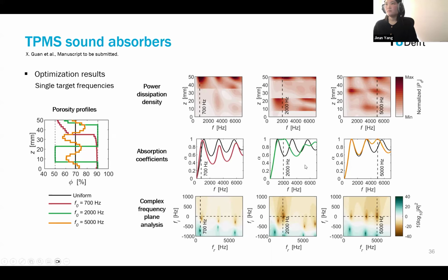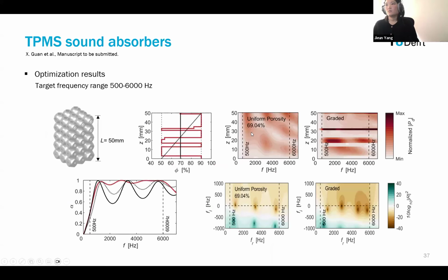And also this one in the middle was a little bit of an extreme case, because we were trying to improve the sound absorption coefficient, which was at quite a low value, to a higher one. So the optimization produced this very jumping profile to move this peak frequency and also increase the dissipation. Yeah, so we thought it helped a little bit in understanding how we obtained this very jumping porosity profile. So the optimization was in the end trying to shift this absorption peak and also increase the dissipation inside the layer. So it generates these low porosity values to change the tortuosity inside the layer and also improve the dissipation at certain locations.